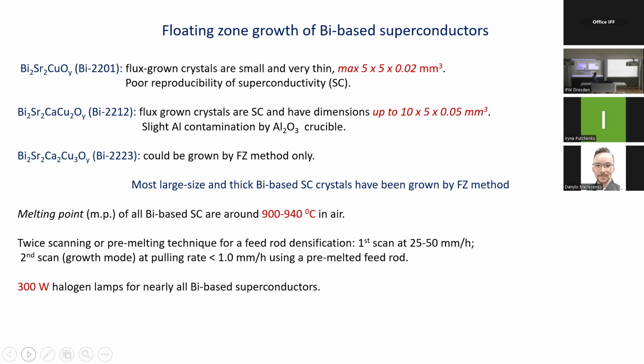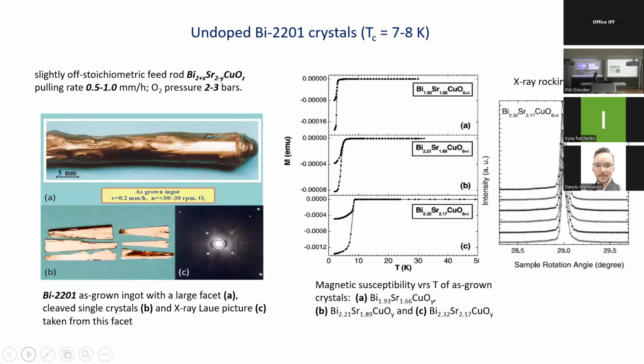It is done at much lower pulling rates, below 1 millimeter per hour. And in this way, we could stabilize the zone and get crystals. So first, undoped bismuth 2201 crystals with the highest TC of 7-8K. For the growth of bismuth-based superconductors, we always use slightly off-stoichiometric feed rods. They're a little bit bismuth rich and strontium deficient. Of course, we should pre-melt this feed rod and then apply a growth rate between 0.5 and 1 millimeter per hour, or even lower.